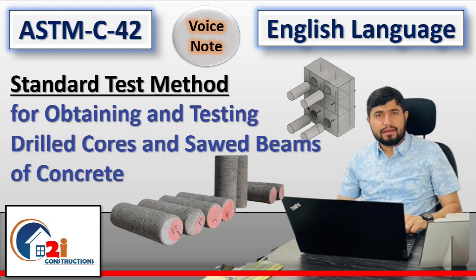Now, what is the acceptance criteria as per ACI 318? I think 5.6.4.4, because yesterday someone asked me. The acceptance criteria: the average of these cores shall not be less than 85% of the design compressive strength of that structure. For example, if we have 5000 psi, the design strength is 5000 psi. After testing, the average of the 3 cores should not be less than 85%. But none of the cores shall have a compressive strength less than 75% of the design compressive strength.